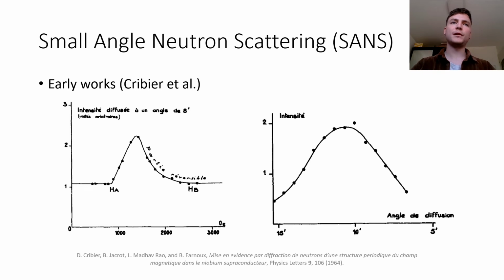And in Cribier's experiment, he measured the intensity of the diffracted neutrons at an angle of about 8 arc minutes as a function of the applied field, which is shown here. And he also measured the Bragg peak intensity at different diffraction angles at an applied field of 1620 Oersted, which is shown here, and 1620 Oersted is already in the vortex phase. And we can see very nicely here that the vortex phase is actually not stable. It decays little by little with more magnetic field, which I will also show a little bit later.